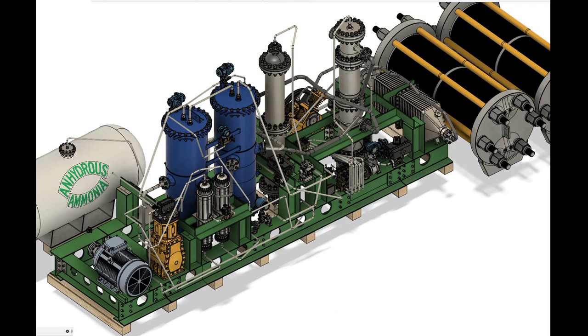Interestingly, because of the small size of the plant, the major components that require machining can be produced rapidly and at very high volumes. It bears repeating that the dogma of bigger equals better is entirely overturned here, since small components translate into much easier manufacturing, and the potential to tap into vast supplies of mass-produced components. Since a small ammonia plant does not require a high flow volume, unlike large-scale plants which use flanged connections, small-scale units would make use of mainly small threaded fittings, rated for high pressure and constructed entirely from 304, 310, or 316 stainless steels, and machined with 4-axis vertical machining centers.